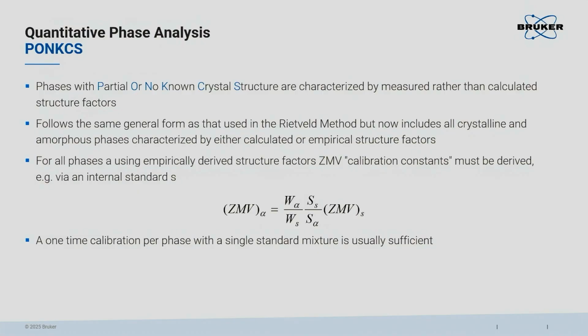quantification method there is at this point in time, simply because you use observed intensities to describe the intensity distribution of your sample, while the Rietveld method is using calculated intensity distributions. So the Rietveld intensities are only valid if your crystal structure is correct and representative of your sample. If that's not the case, then you of course introduce errors. With measured intensities, you get over that problem.